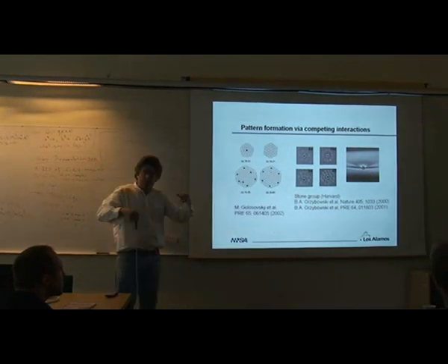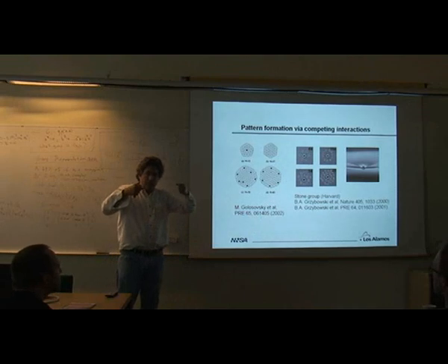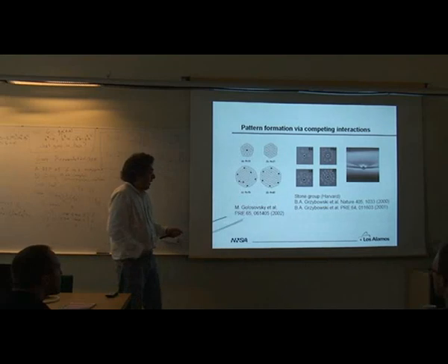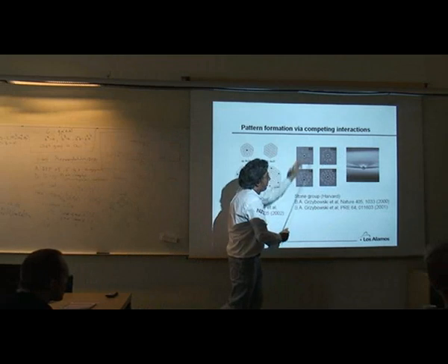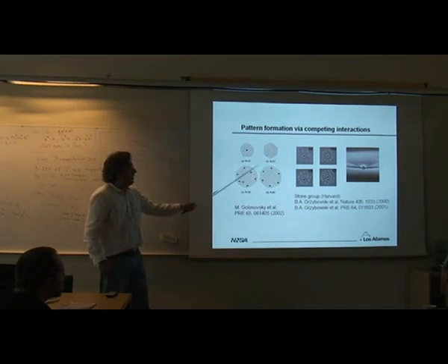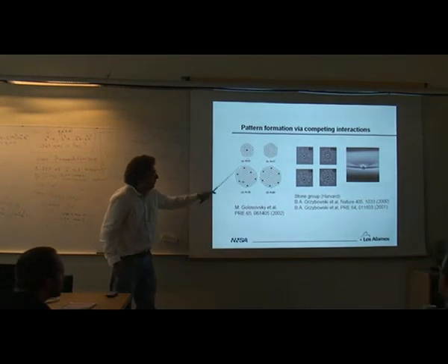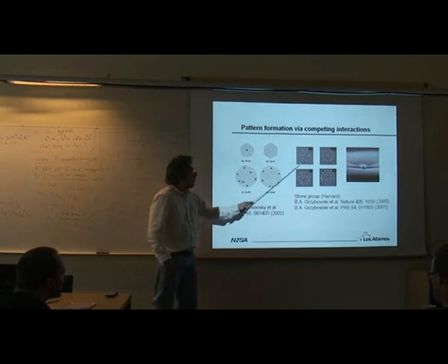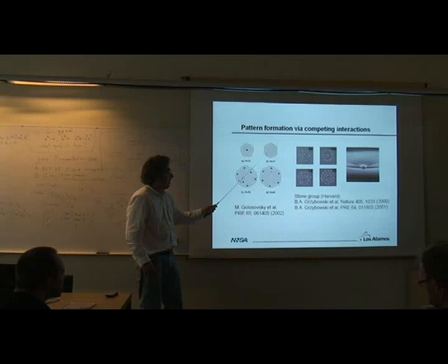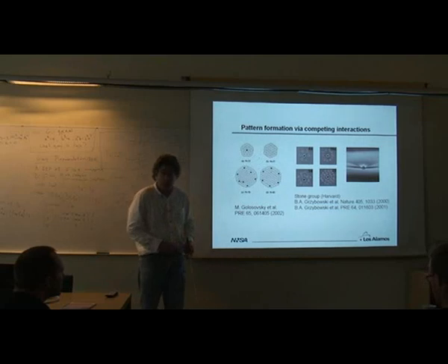So it's sort of like what they call the Cheerio effect. In cereal, you put some solid objects in your milk, and over time they come and stick together. Right? And so what they were studying here is that you can get these cluster phases. So they generally come in, but they can't completely collapse. But they find if you do this over and over again, there are certain clusters they call magic clusters, such as if you have 37 particles, provided that they're all the same size, same charge, it can form this hexagonal subpacking. So what are the particles in that particular case?